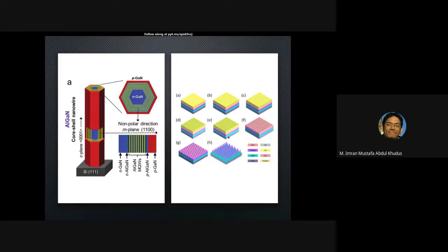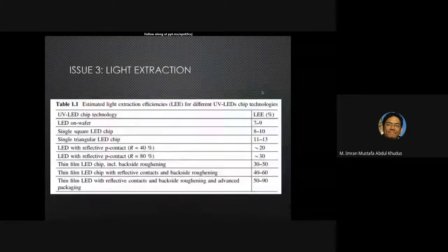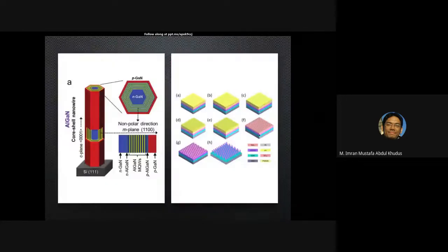The main issue is that it's difficult to interface with. If you think about your LEDs as just being something like this, and you have these nanostructures which are really small, it's fairly tricky to work with them on a large scale, so this approach is not that popular in industry. There are groups more inclined and less inclined to industry, but they do work. The advantage is you don't get dislocations. The dislocation density is really small on this. You have other problems, but the dislocation is small, right? So it's one of the options.